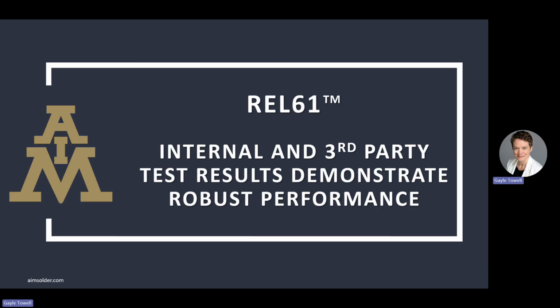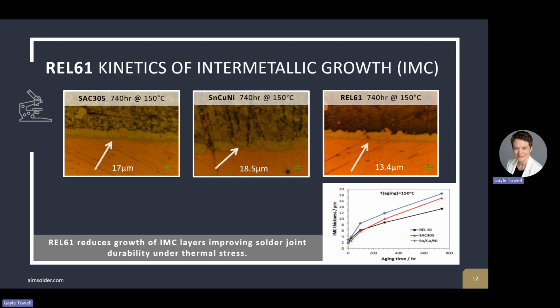We have a whole host of internal and third-party test results which demonstrate REL61's robust performance. This is just a very brief overview of some of those results. So if we look at intermetallic growth, REL61 reduces the growth of the IMC layers, which improves solder joint durability under thermal stress. Here we see it compared with SAC305, a tin silver copper alloy. And we see that REL61 has the smallest intermetallic layer of the three.